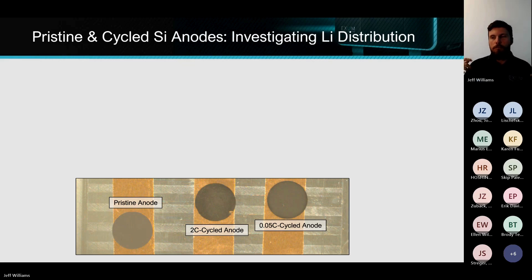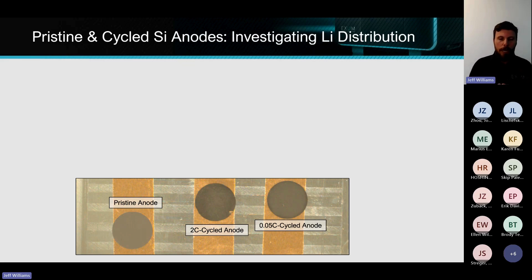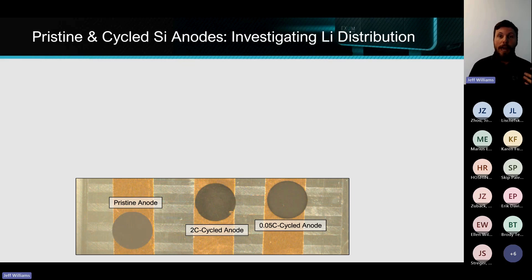Normally this failure is found in the form of lithium plating or lithium dendrites, where you have lithium plating out, ultimately short-circuiting the battery — and the battery fails, which we don't want. So how do we stop lithium plating, where can we see it, and how can we see it?